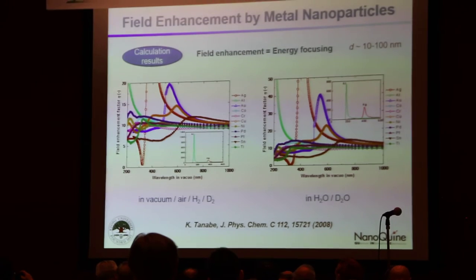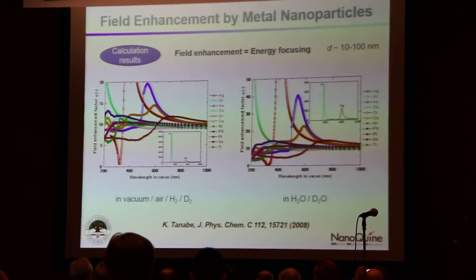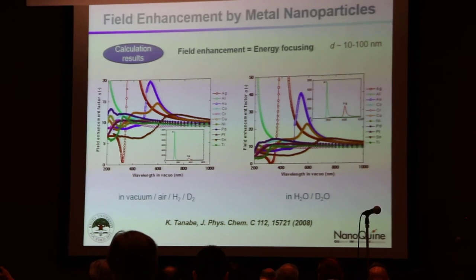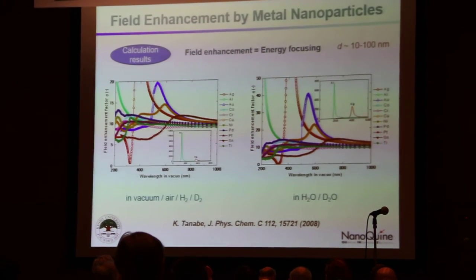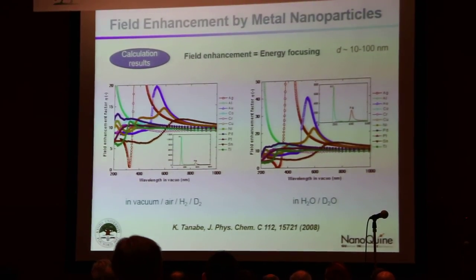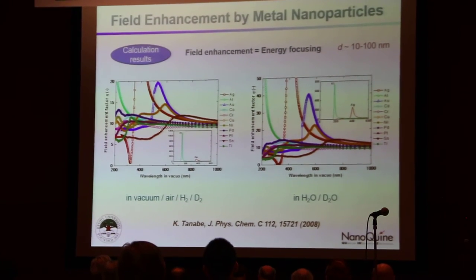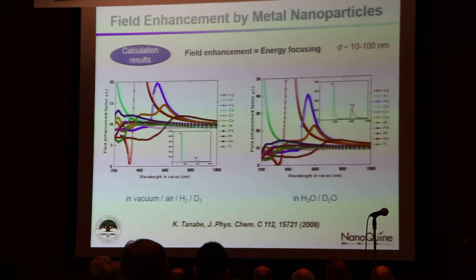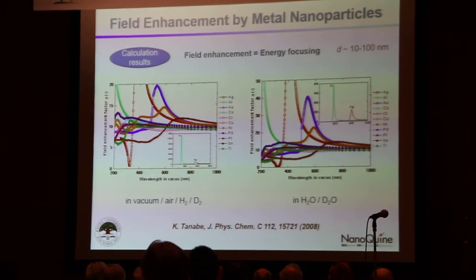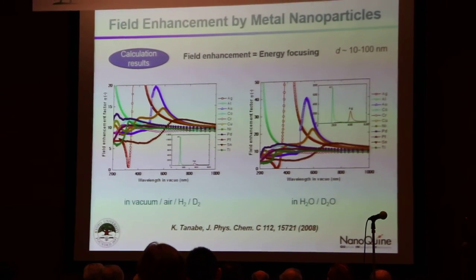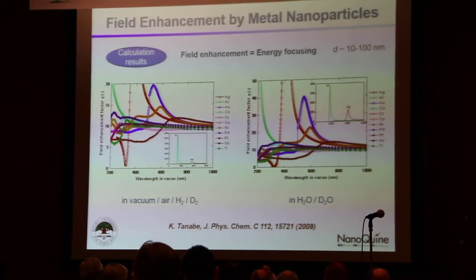This is the calculation result. We can see that for a variety of metal elements we can have more than 10 times enhancement of the field. This can be applied for the liquid phase experiment because they apply an electrochemical method and the field is enhanced around the metal nanoparticles. For both liquid phase and gas phase experiments we can expect that by utilizing metal nanoparticles we can enhance or localize the energy of the electromagnetic field around the metal.